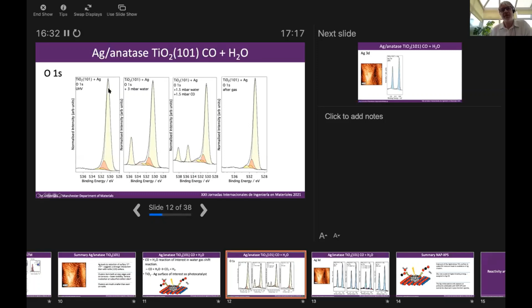When we reduce the water pressure to a half, so that we go from 3 millibar of water to 1.5 millibar of water and add in 1.5 millibar of carbon monoxide, we get some additional peaks. I should have pointed out, this is the gas phase water, and this is the gas phase carbon monoxide now. We see very little difference actually in the oxygen 1s spectrum. This is our subsurface defect peaks, this is our oxide substrate. This is adsorbed molecular water, so there's slightly less of it because the pressure is lower, as you would expect. This we think is the hydroxides, and this is probably some carbon oxygen species. And when we pump away, we're left only with the carbon oxygen species and the hydroxides. So the oxygen didn't really tell us very much, not very exciting, but the silver was slightly more interesting.